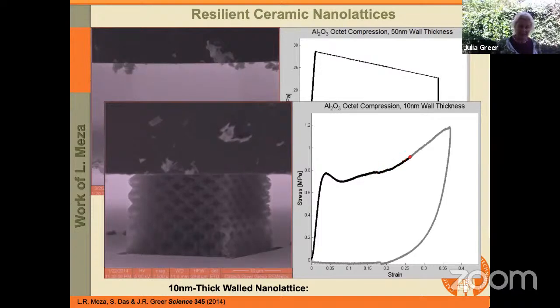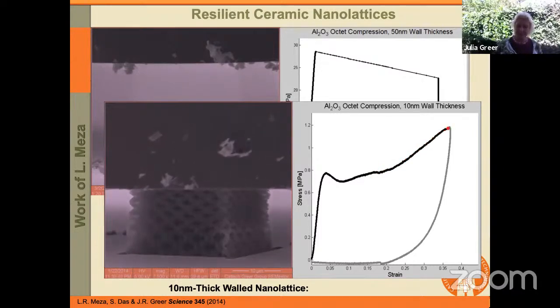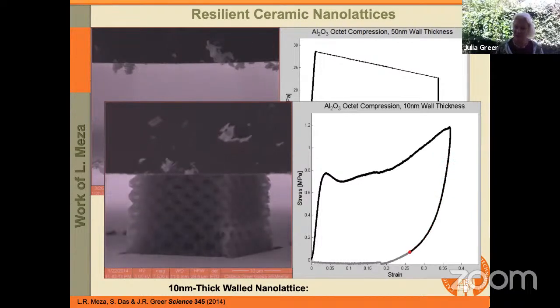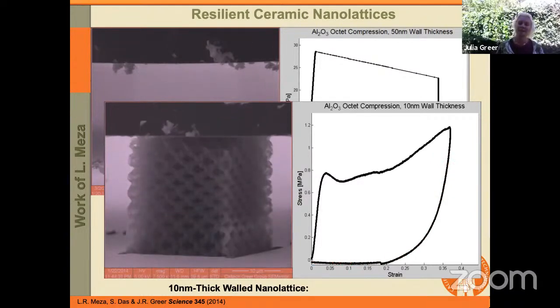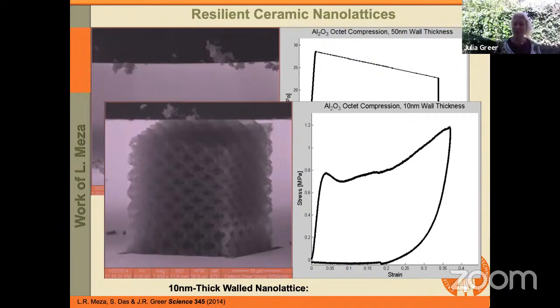You can see it compressing, compressing, compressing. And then just as we're expecting it to fail, you can see what happens. This particular material thinks of itself as a sponge. So you can see very clearly exactly the same experiment, exactly the same architecture, two very different responses, all as a result of the wall thickness reduction. So if that doesn't convince you that there is in fact a size effect, then I should just stop this topic right now. So of course this fully recovers.